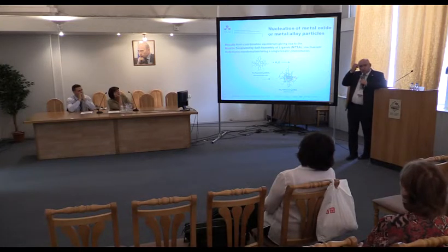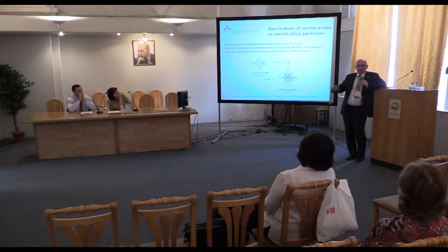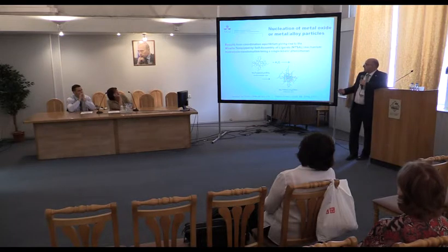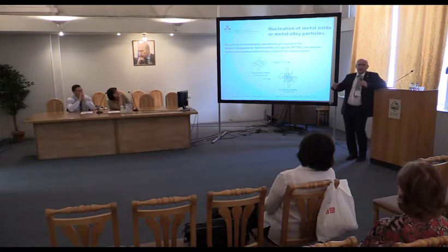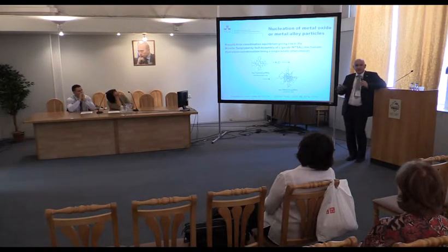What is also very important is that for metal oxides there is no memory between different steps of this equilibrium. The structures which are produced are not kinetically controlled, they are not like organic molecules where some group is replaced. In this case, there is a total regroupment of cations and anions, and in each case, what we see is a result of dense packing of cations and anions.